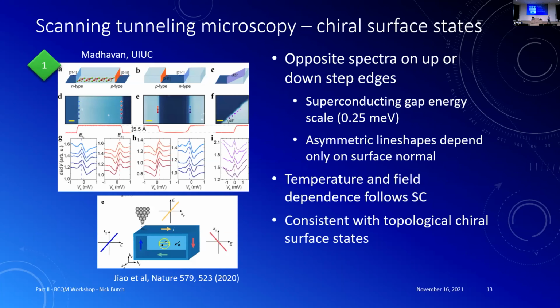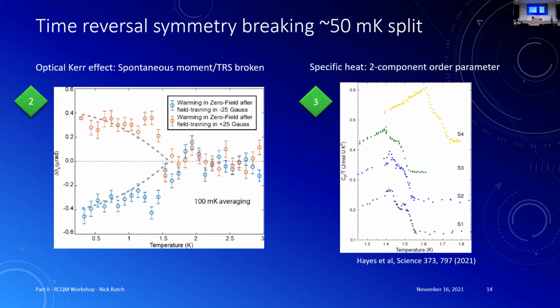And so quickly, Vidya Madhavan's group did the STM measurements, and I will not claim that these are completely understood, but when you look at step edges on the surface that have different directions, either up or down, you always get opposite, not sign, but sort of mirror image tunneling spectra, and this is by definition chiral. Okay, the energy scale of this is correct for superconductivity. It goes away when the superconductivity is gone, and so this is a signature of something to do with the superconductivity.